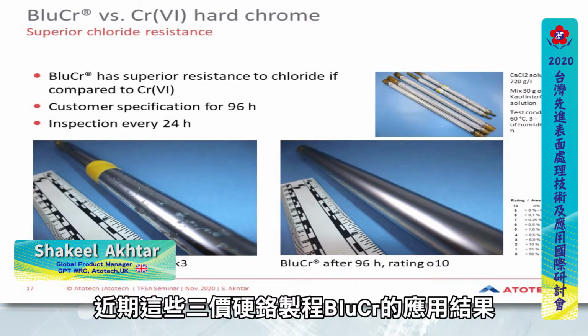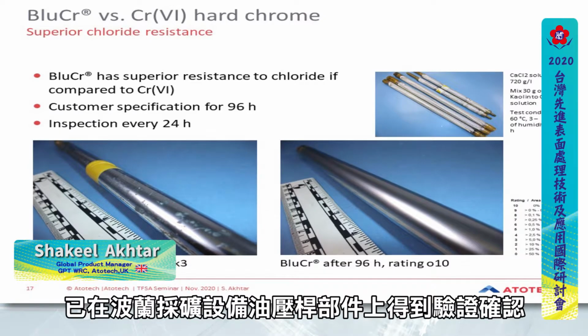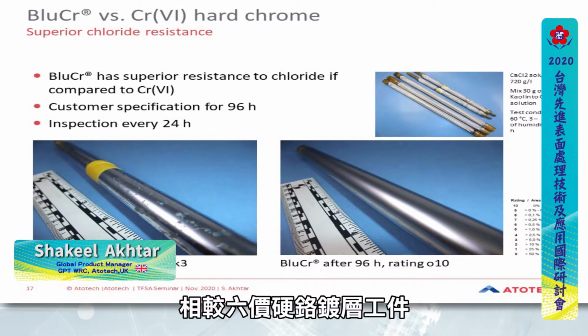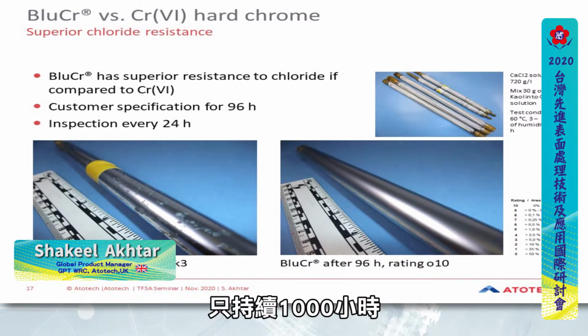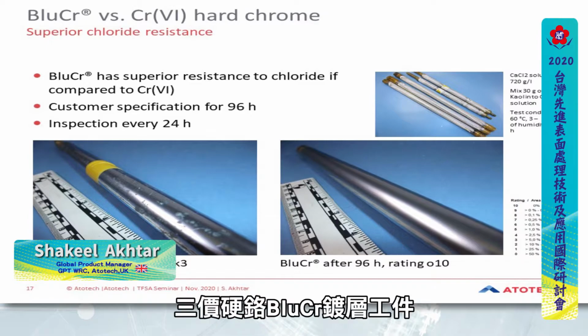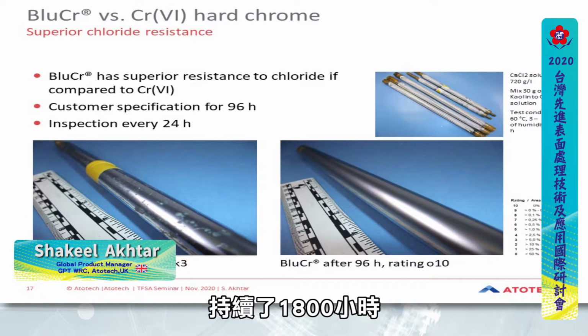These results have recently been confirmed in service on hydraulic bars plated with blue chrome and used in mining equipment in Poland. Blue chrome in this scenario lasted 1800 hours compared to chrome 6 plated bars, which only lasted for 1000 hours. So we get a factor of 1.8 increase in service life.